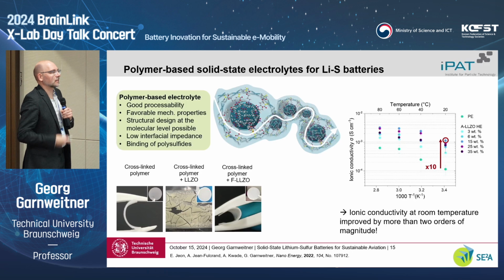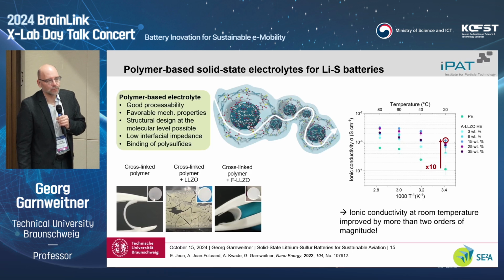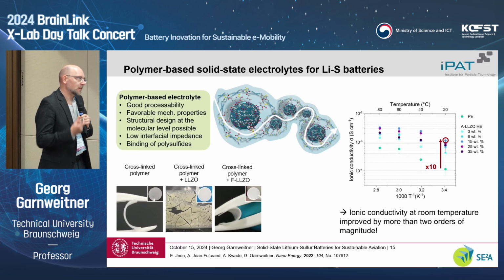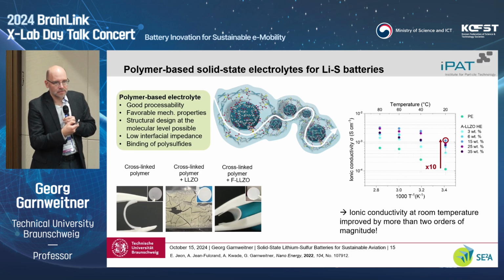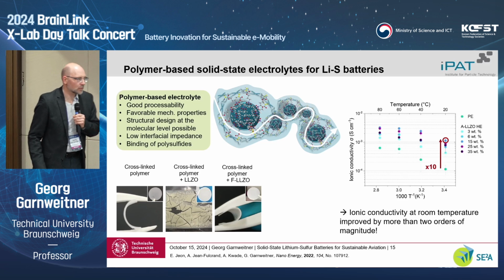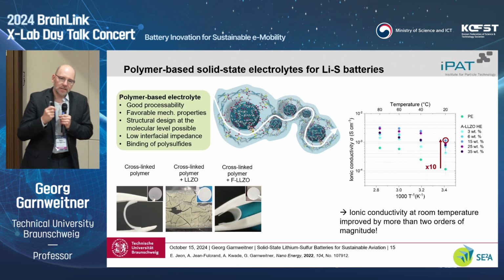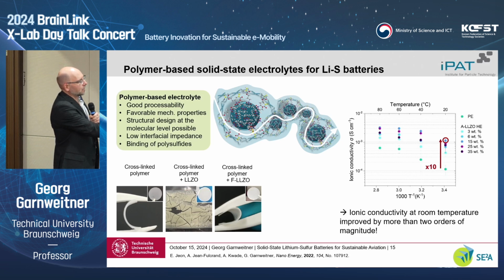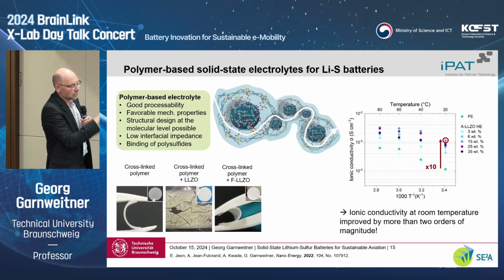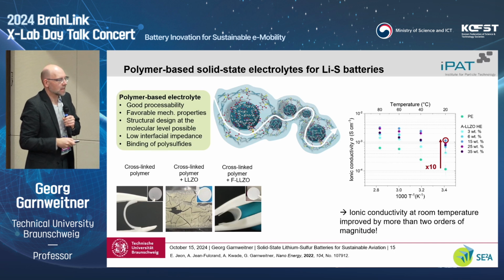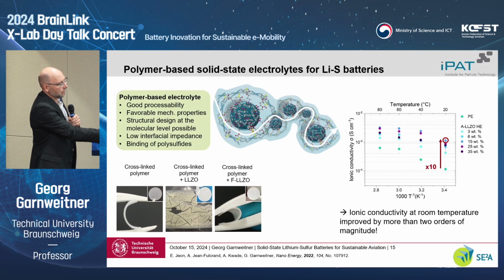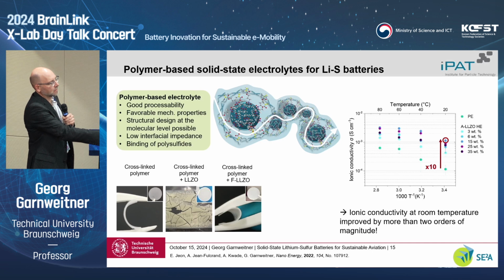We have to add some other component, and here we decided to go to a hybrid solid electrolyte, where we additionally add ceramic particles, lithium lanthanum zirconium oxide. These you have to modify on their surface. That's why we call them FLLZO. This is a type of functionalization that we used. And you see then we again have a flexible system. If you incorporate the pure particles, it's very brittle and you cannot process it. But after the surface modification, it becomes flexible. And we again have a 10-fold increase in the ionic conductivity.